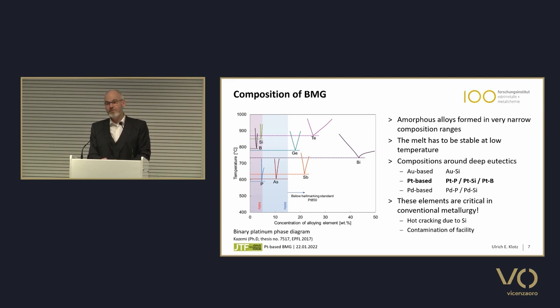And of course, this is also interesting in terms of the processing, because some arguments that you have for melting and casting platinum, high stability of the refractories, etc., are probably not true anymore if you can lower the temperature that much. But you have to keep in mind these elements are very critical. If it crystallizes, it's not good. It will be very brittle.